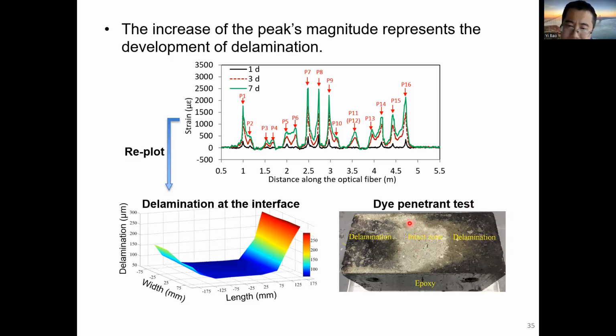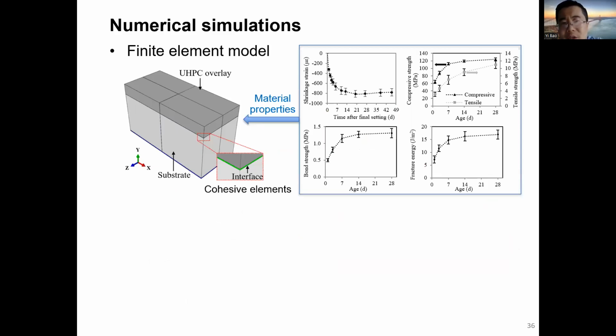So as you can see, in the middle of the specimen, there was no delamination, and at the two ends of the specimen, we observed the delamination. This is consistent with our fiber optic sensor results. And then to further understand the early age delamination problem, we created a three-dimensional finite element model.